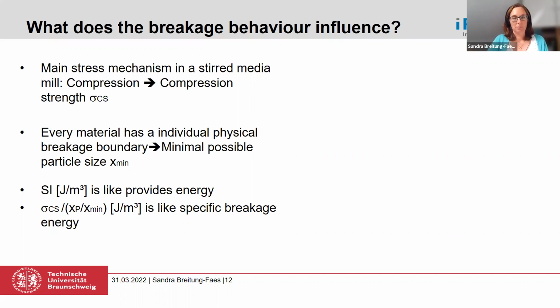As we know from the literature, the particle size itself will also play a role, because with decreasing particle size, the resistance against breakage is increasing. And each material has a certain physical grinding boundary, which means at some stage of grinding, the particles get that small that they are not able to store any more energy. And so they are not able to break anymore. And so I took up these 3 parameters and put them together in one, let's say, material specific value describing the specific energy which is necessary for breaking. So I took this compression strength and something like, I said, a dimensionless particle size, which is taking into account the grinding boundary and the current status of my particles.